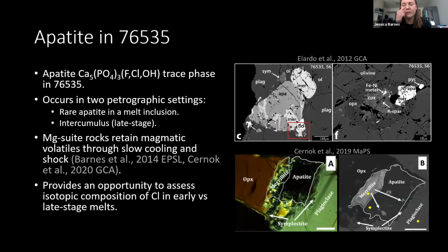So we were most interested in looking at the apatite in this sample. We'd looked at it before in the 2016 paper and subsequent to that as well, and it showed those heavily fractionated chlorine isotope values. But the interesting thing about this particular sample is that apatite doesn't just occur in intercumulus regions like you can see here, but there's also a melt inclusion that also contained apatite, an apatite-merrillite intergrowth or pair, within the melt inclusion inside an olivine crystal.